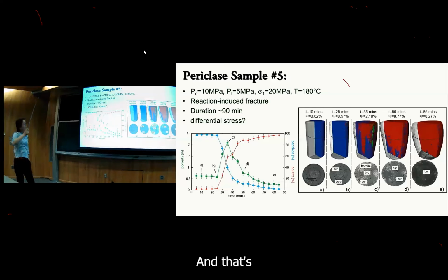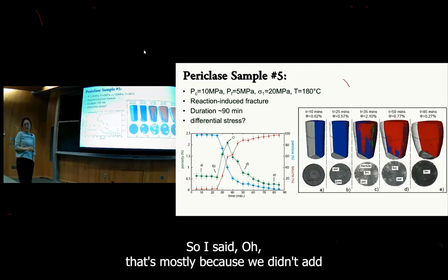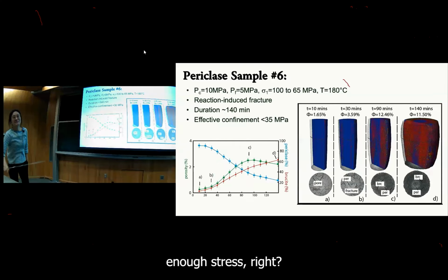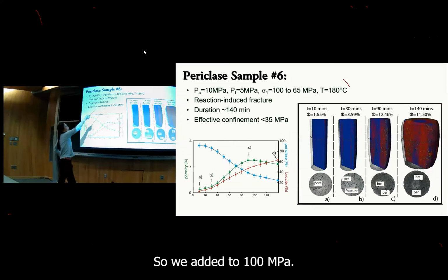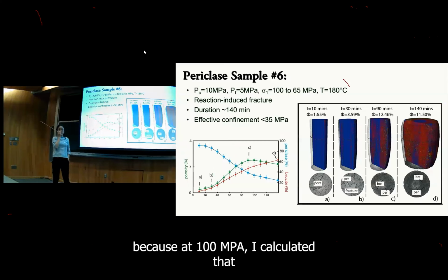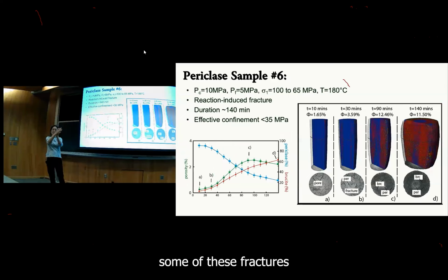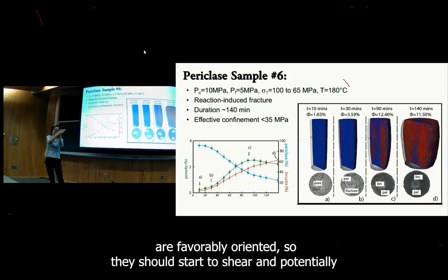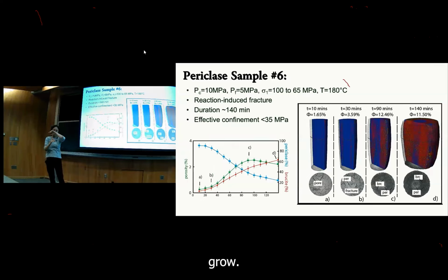So now the sigma 1 along the axial direction increases from 10 to 20 MPa. And that actually behaved very similar to when we didn't have that added 10 MPa stress. So I said, oh, that must be because we didn't add enough stress, right? So I added up to 100 MPa, because at 100 MPa, I calculated that some of these fractures, if they are favorably oriented, should start to shear and potentially grow.